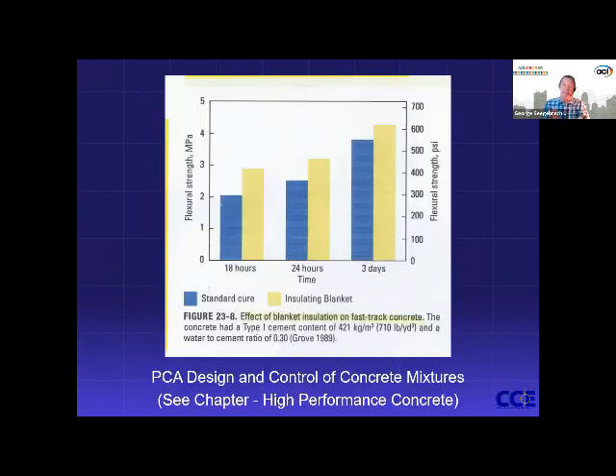So as an example, here is a slide taken out of PCA's high performance chapter, where we have a side-by-side comparison of a type 1 mix that was used for repair, fast track, with 710 pounds per cubic yard cement, type 1, and a 0.3 water cement ratio. So it is high performance. And 18, 24, and 72-hour strength development are shown here for flexural strength. Notice how the insulation blankets, the yellow bar, is so much higher. Now, you didn't pay any more for that mix. Of course, a little bit you're going to have to pay for the blankets and the labor to put them on. But money well spent, I would say, especially in a fast track, say, if this is a pavement reopening where time is of the essence, the blankets pay off big time.